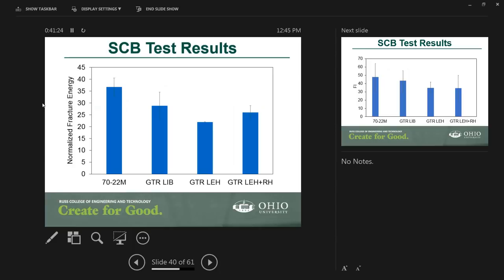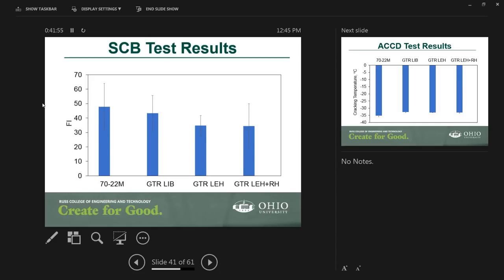The SCB normalized fracture energy, which is an indicator of the fatigue cracking resistance, showed a drop in the GTR mixes as compared to the polymer modified. But one thing I would also like to note is that in certain cases the variation was high, so that statistically that difference is insignificant. And this is also another parameter, the flexibility index. It tells you more about the ductility of the mixture, or how it can tolerate stresses after the material cracks.